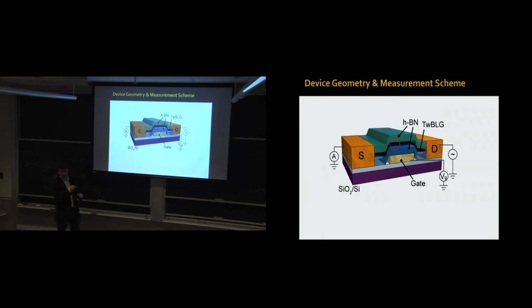Very importantly, we have a nearby metallic plate, a metallic electrode, that forms a parallel plate capacitor with the graphene system. So when we apply a gate voltage to the system, we can vary the charge density on one of the plates of the capacitor. One of the plates is the graphene, so we change the charge density on the graphene with the voltage knob. That's very important.